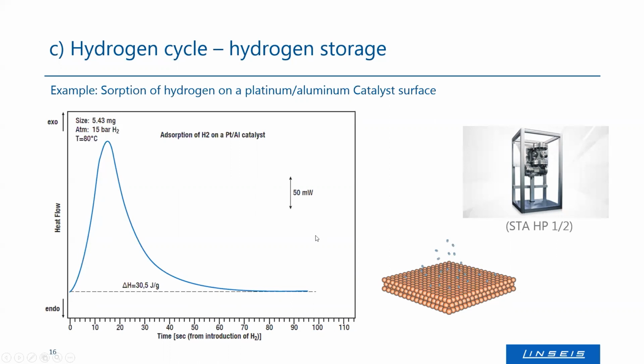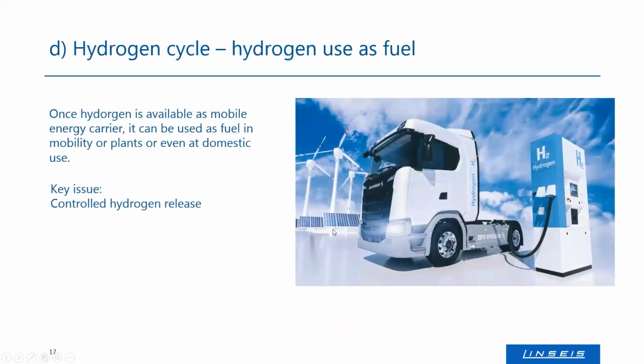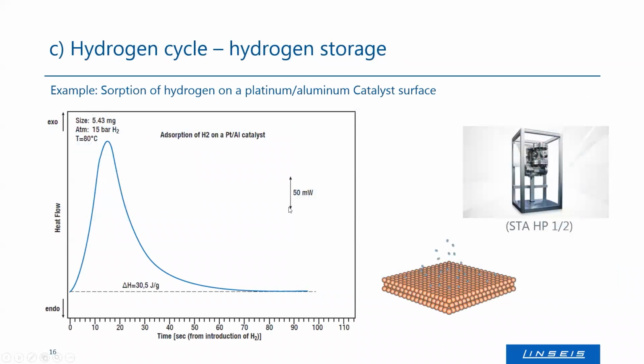And what we also did, which comes on another slide, sorry for that, is we had a lot of adsorbers where we just measured the weight change. In that case, we already measured the heat absorption, which is also possible with a TG-DSC instrument.